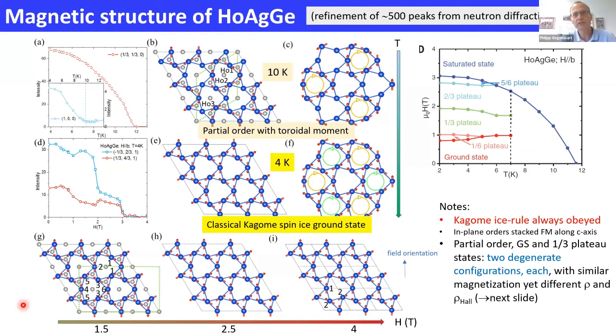And so let's start with this range of the phase diagram below where the magnetic order develops below 12 Kelvin. So these are data taken at 10 Kelvin, and there a partially ordered magnetic state was found as a result of the refinement, where you see that in each triangular unit there is always one spin pointing inwards and one outwards, and the third spin is not yet ordered.